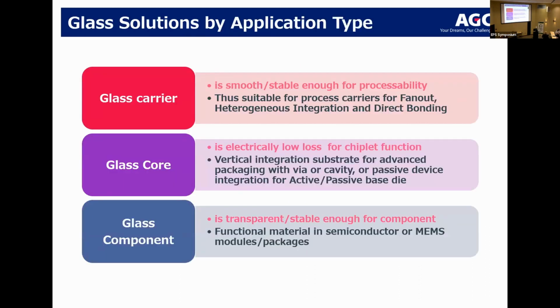Okay, so the three main applications for glass are glass core, carrier, and glass components, and each one has its own unique set of characteristics. Glass carrier, you have to match the CTE of the glass, so it doesn't warp when you mold it. The glass carrier also needs to be matched to the molding compounds that are needed. Then you release it, and then you use the glass over again.